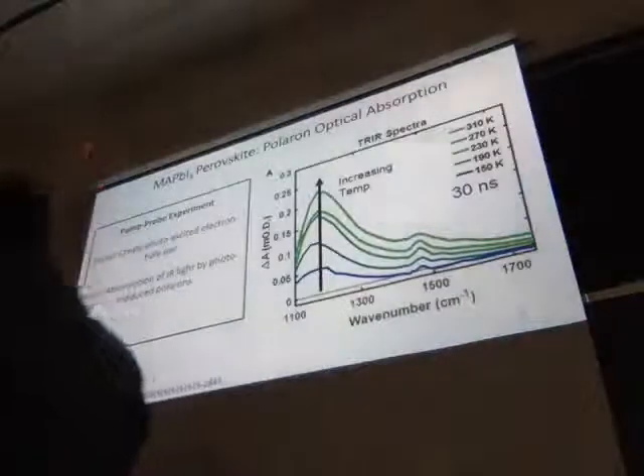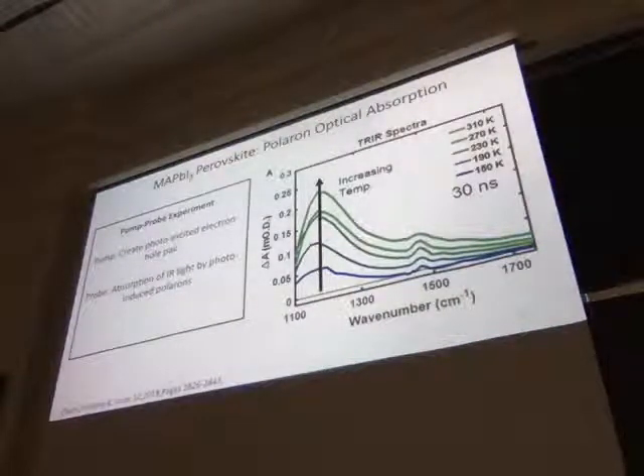This figure just shows experimental results for a close cousin of the material we're looking at. They have a little bit different chemistry, and they're not nanocrystals, they're thin films. But they do pump-probe experiments to look at the time-resolved IR spectrum. The simple idea is that they photo-excite it at a high energy, like 2 eV, to create the polaron, and then they probe it with IR frequencies to look for absorption characteristics.